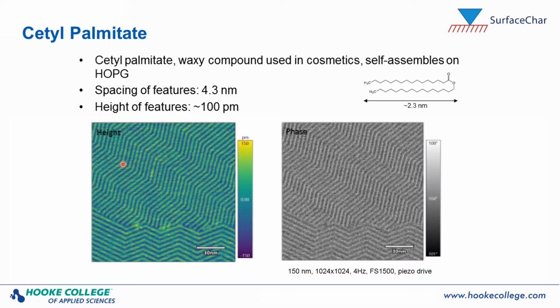And then finally, this example of a self-assembled monolayer of this long chain hydrocarbon. It's called cetyl palmitate. And it self-assembles onto a highly ordered pyrolytic graphite surface. And so this is a height image, and this is a phase image in tapping mode. And what you're seeing is a self-assembly of single molecules here, where these features are spaced apart. These features, the lamella in these molecules, only by 4.3 nanometers. Their height is 100 picometers. And you can resolve it also in the phase image.